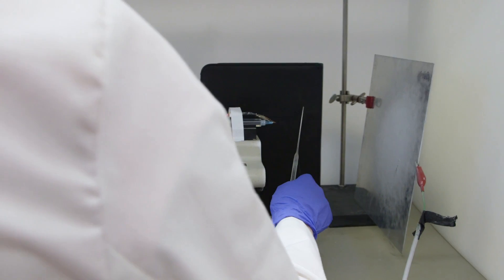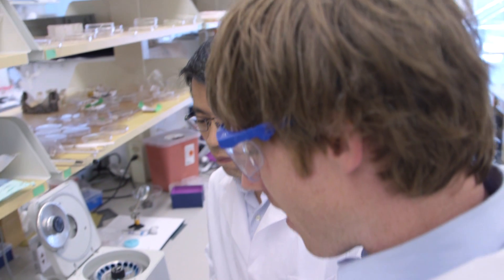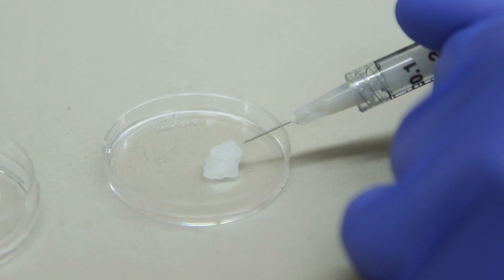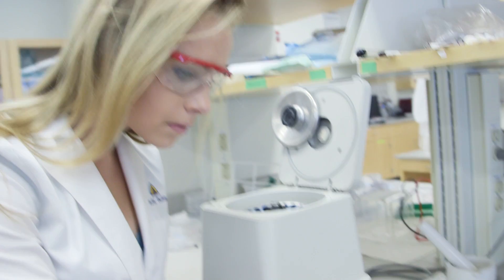Our product is really a composite where we have a hydrogel component and we have our nanofibers — these short fragments of a biodegradable suture-like material dispersed throughout the volume. Most current tissue fillers are hydrogel-based, but we are using the fiber as a reinforcement component to provide mechanical strength into the hydrogel matrix. What's really innovative and exciting is it feels just like your body's own soft tissues, yet it's still cell-permeable so that cells can grow into it, and the nanofibers are able to mimic the design of the native tissue structure.